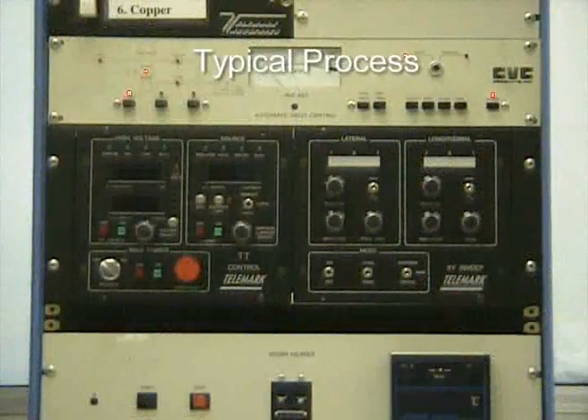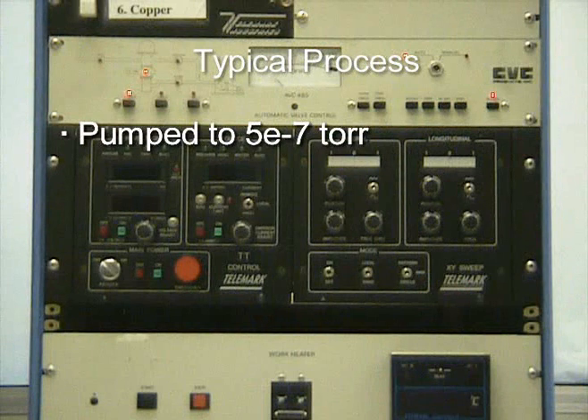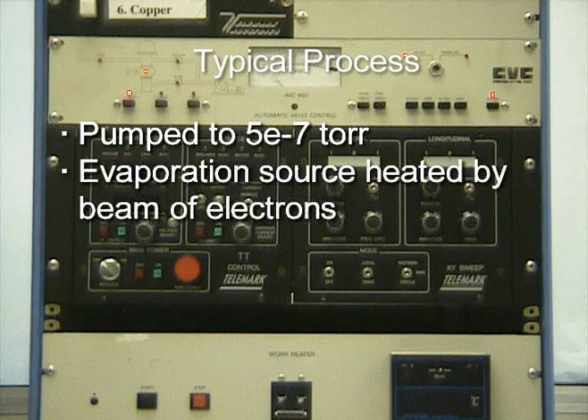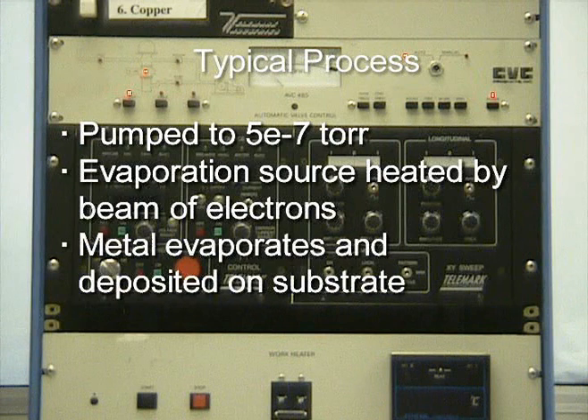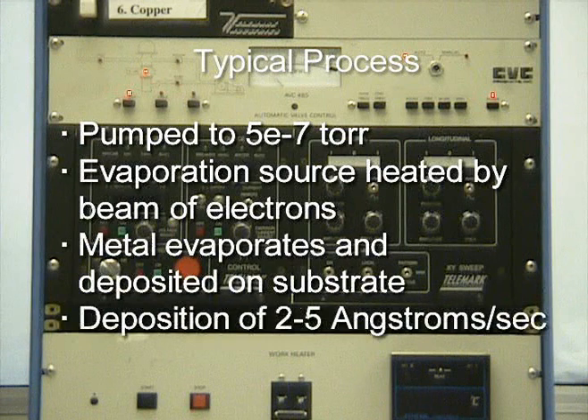In a typical process, the chamber is pumped down to a pressure of 5 × 10⁻⁷ torr to prevent air molecules from interrupting metal atoms as they travel from the evaporation source to the substrate. The metal evaporation source is then heated to a high temperature by a beam of electrons. This causes the metal to evaporate and be deposited on the substrate. Typical deposition rates range from 2 to 5 angstroms per second.